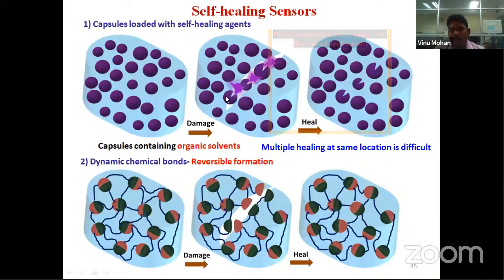what will happen is, these capsules are loaded with the healing agents. So that capsule releases these solvents, and locally it will undergo reorientation of binder and conductive filler particles. Basically, we have to choose these healing agents carefully. Whichever binder we used, we have to use the compatible solvent, and we have to make sure these capsules are not affecting the electrical conductivity or the electrochemical property of the electrodes.